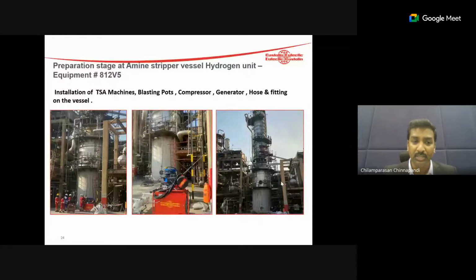Then you are forced to change the complete vessel. This is going to be a huge cost, with downtime and the non-availability of the plant, and so many other things. So what we do at Castolin is coat the vessels with Inconel, Stellite, Hastelloy, or other wear resistant spray coatings to bring the characteristics required to maintain the parameters of the vessels. For example, the vessels require erosion and corrosion resistance at a high temperature of 650 degrees.